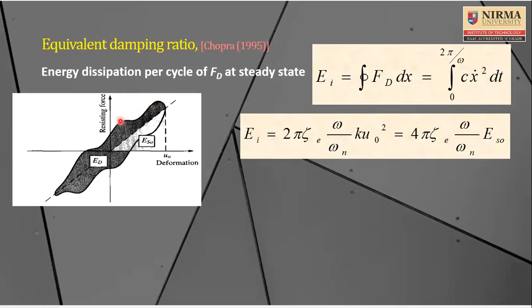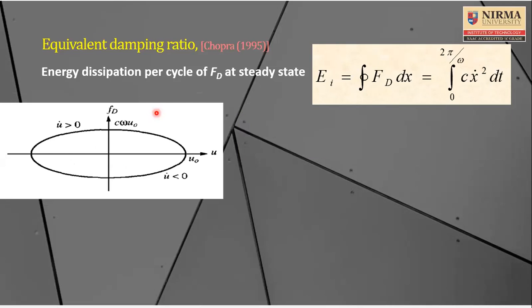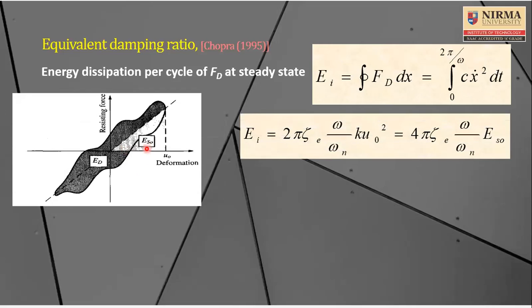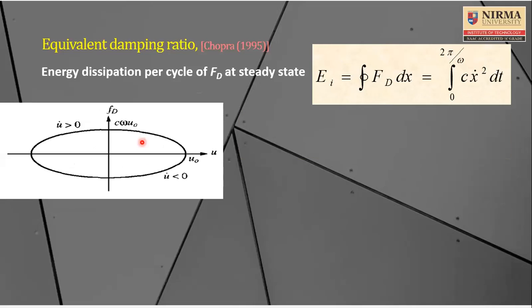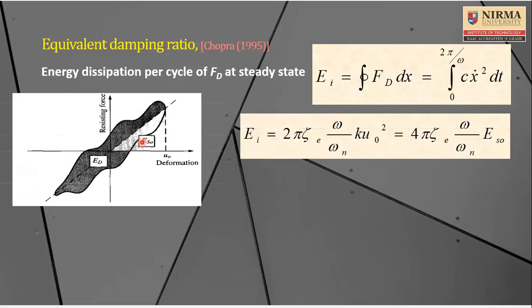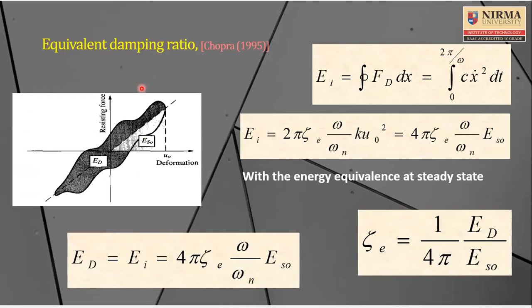So now you have a hysteresis loop available which is non-regular, and you calculate the energy using a numerical integration method and calculate the energy dissipated in one cycle in such a hysteresis loop, and you equate that with a sinusoidal curve where you apply a harmonic periodic load to the element. You convert it into an equivalent load by equating the energy of a typical hysteresis loop with an equivalent damping ratio, or equivalent viscous damping, as you can see from some of the mathematics here.